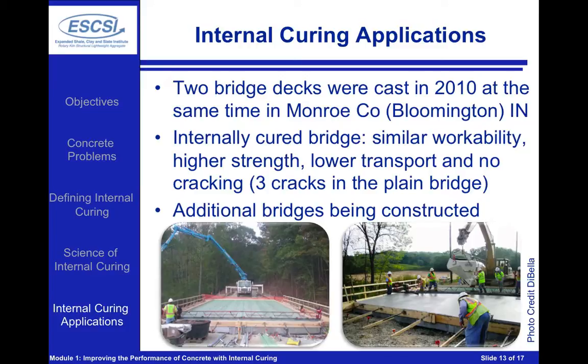Further, we've seen some internal curing applications in the state of Indiana. Here we see two bridge decks that were being cast at the same time in 2010. These two bridge decks were to compare a conventional bridge deck mixture and an internally cured bridge deck mixture. Both mixtures had similar workability. They both had similar strength. The internally cured has slightly higher strength.